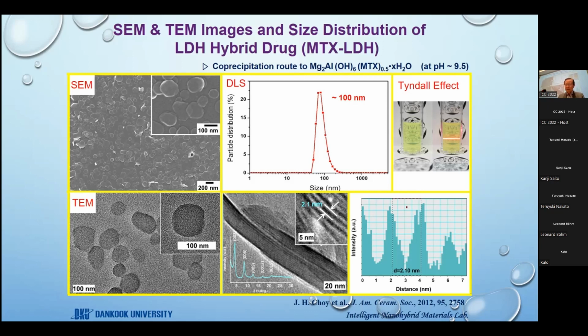As you can see in the SEM and TEM images, the average particle size of MTX LDH was determined to be around 100 nanometers, which is in good agreement with the particle size distribution results obtained from the Zetasizer. In the cross-sectional high-resolution TEM image here, the interlayer distance between periodic lattice fringes from the 003 planes is approximately 21 angstrom, which is in excellent agreement with the XRD results.